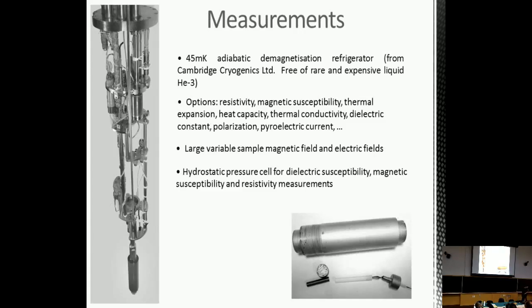So we can investigate these materials experimentally. We did measurements on a 45 millikelvin adiabatic demagnetization refrigerator, where you can do very nice, precise, smooth sweeps in temperature from low temperature up to room temperature. And this is fitted with miniature coaxial cables to measure the capacitance of the sample, which is proportional to the dielectric susceptibility. And also for later, we did measurements in a piston cylinder pressure cell.